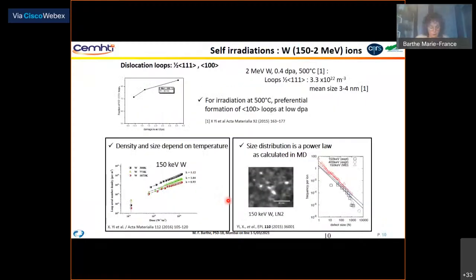So first, there are a lot of studies which are dedicated to dislocation loops, the observation of these defects in self-irradiated tungsten. And it has been shown that 2 types of loops are created, and their density could reach 10^22 per cubic meter at 0.4 dpa at an irradiation temperature of 500 degrees C. And also there is a preferential formation of the 100 loops at low dpa. It has been demonstrated that the density and size depend on the temperature, and also that the size follows a power law, as has been calculated using molecular dynamics.